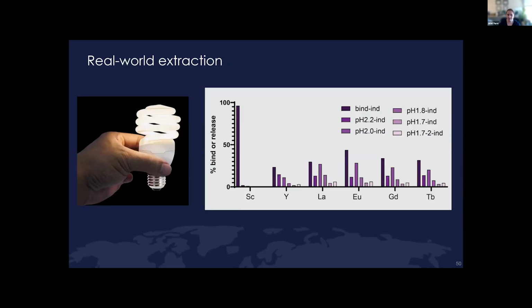So where do we go from here with this? Well, as you noticed, that last one was just a mix of lanthanides. So I walked into lab one day and my postdoc and one of her undergrad mentees were standing at her bench wearing big goggles and holding hammers over a bunch of light bulbs. They were actually able to crush up light bulbs and extract using acid the rare earth from that. When they loaded those onto our column system, what they saw was some specificity for particular rare earths based on the pH. And you can see that with scandium and yttrium compared to these other lanthanides, where this mid-range pH is what releases most of the metal compared to yttrium.